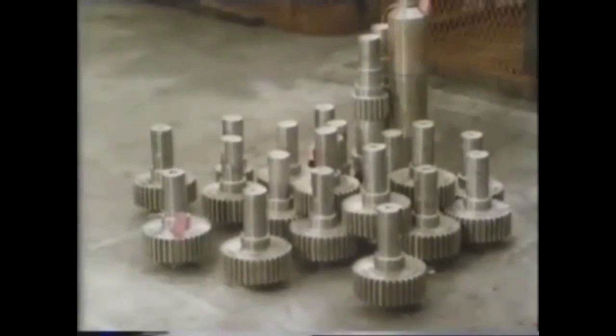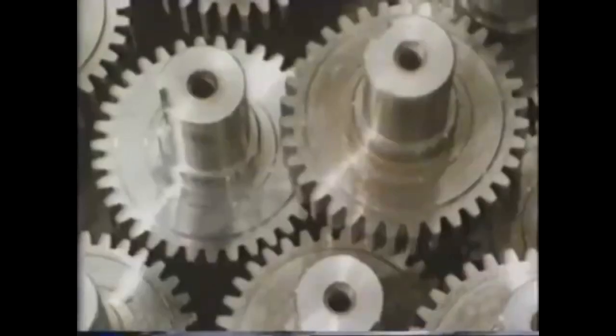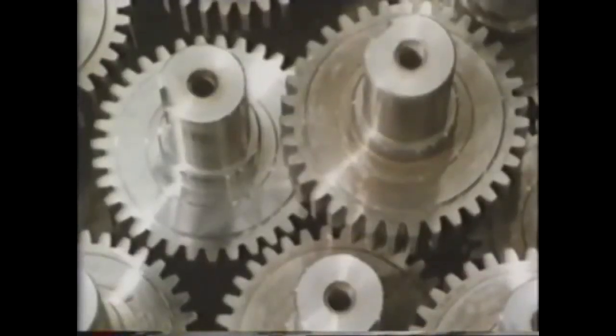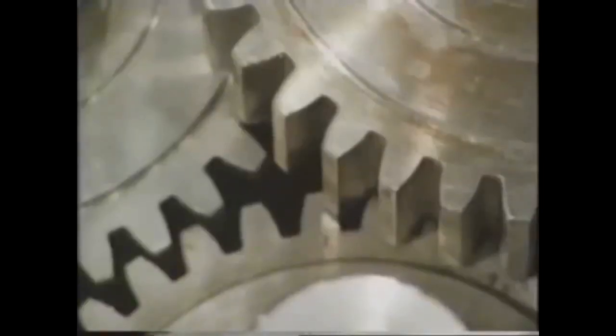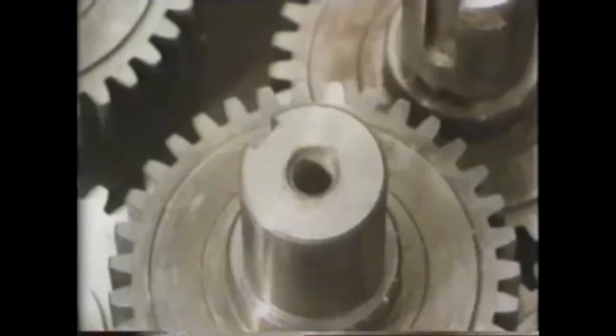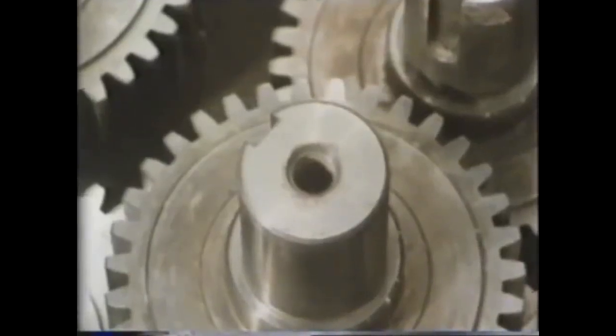Different parts of a component will frequently require varying degrees of hardness. The teeth on these low-carbon steel gear shafts, for example, need to be very hard because they'll have to stand a lot of wear. The core of the material needs to be tough, and the thread in the center of the shaft must remain soft so it won't break when used. To prevent any carburizing of this thread, it's blanked off completely with fire clay.